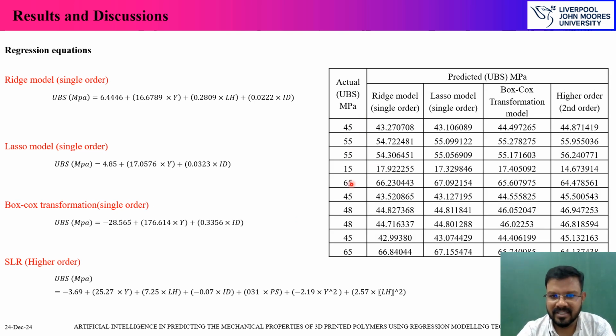So what we see in the first column is the actual ultimate bending strength measured in megapascals by using ridge model. That is, once when we do substitution here for the respective machine settings, the model predicted a value of 43.270 in ridge, and then in lasso the same input parameters were being kept, with which we now got a reading of estimated reading or the predicted ultimate bending strength of 43.106 and Box-Cox transformation of 44.49 and 44.87.